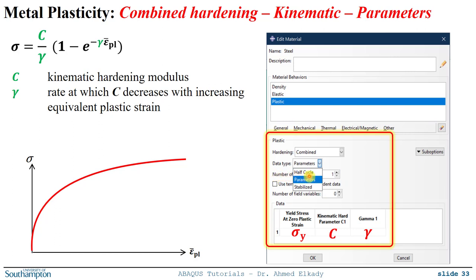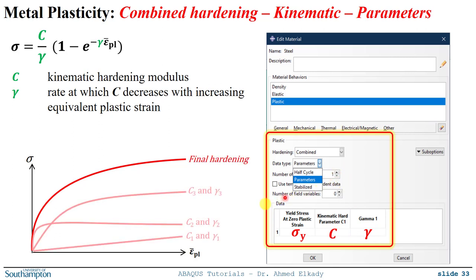You have another option over here, but it's not shown because of the drop-down menu. This is the number of back stresses, and right now I'm using one. Instead of defining this curve using a single set of C and gamma parameters, you can use a number of back stresses. For instance, you can define three different sets of C and gamma, each one defining a different hardening curve, and then ABAQUS is going to combine those three curves together to get the final hardening curve. This can provide a better capturing of the shape of the plastic behavior with better accuracy. But for most applications, one back stress or two at most would be totally fine.